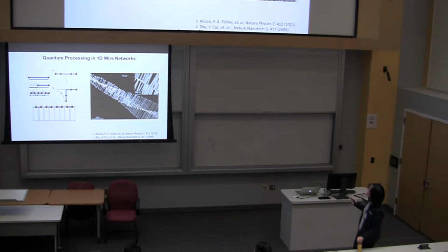It is possible to grow nanostructures that already come highly branched, okay? So here is a growth of lead selenide where you have a main branch that has a screw dislocation threading along, and that creates periodic stress points along the wire, and those stress points become the nucleation centers for the secondary branch growth. So naturally, this structure comes in during growth for some of the systems, okay?